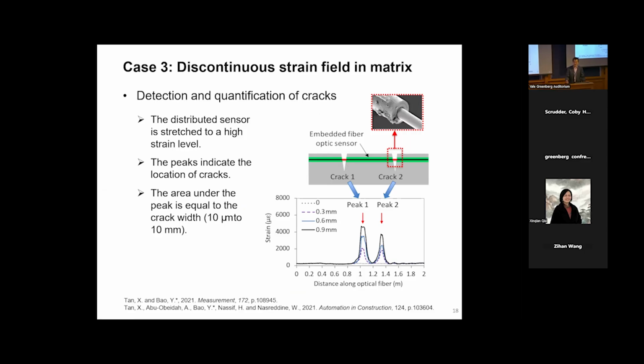But in applications, we often have to deal with discontinuities, like cracks. If the strain field is not continuous, then when the sensor passes through the crack, well, originally I thought the fiber would be ruptured, and then we would not have the signal anymore. But we did the experiment, and we found that actually the sensor didn't fail, because there's a protection layer, the coating. Because of the coating, the abrupt strain change will be averaged over a longer distance. So we were able to detect the cracks as shown as peaks. Each peak corresponds to a crack.